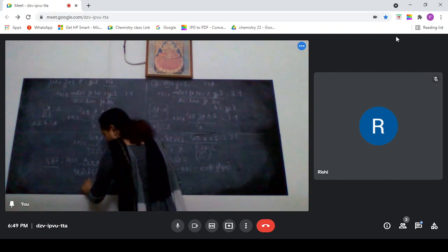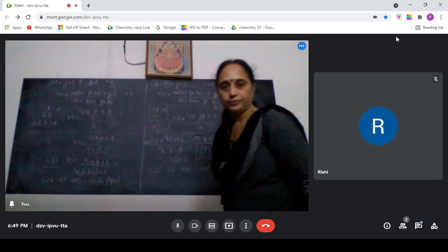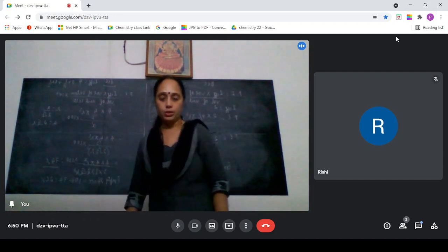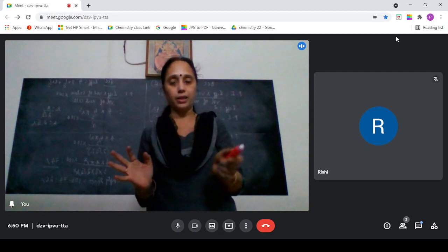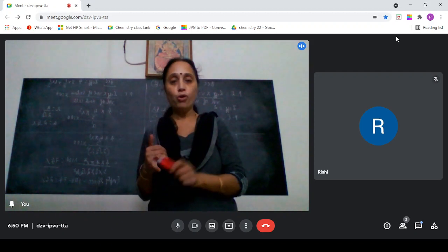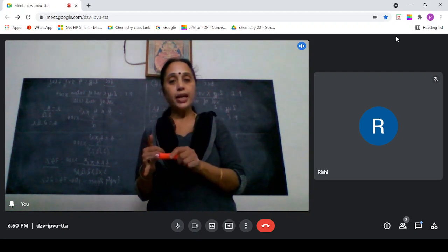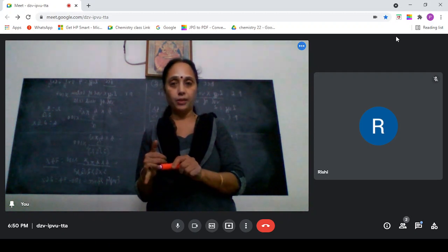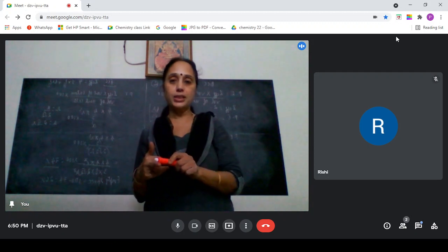So what is the empty space now? Hundred minus 74, 26%. They will ask this in MCQs. Space occupied also can be asked, or empty space. All the three: simple cube 52.4 occupied, 47.6 empty. Body centered 68% occupied, 32% empty. And face centered 74% occupied, 26% empty.